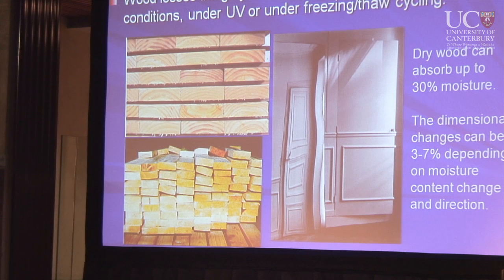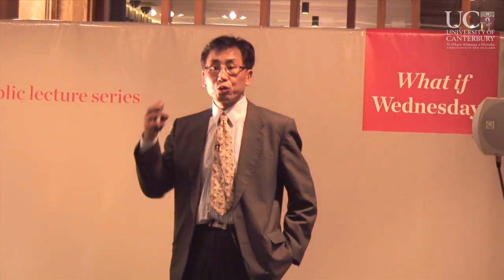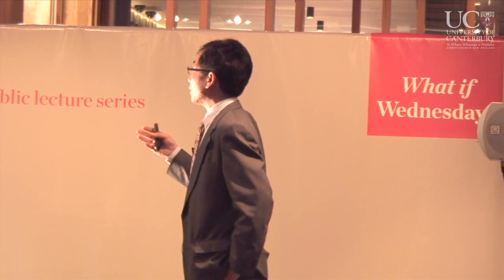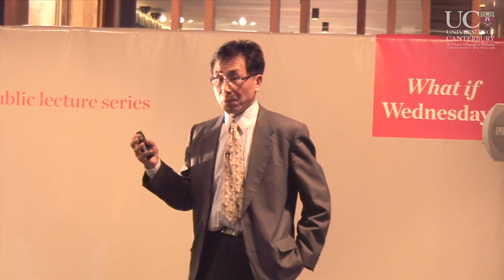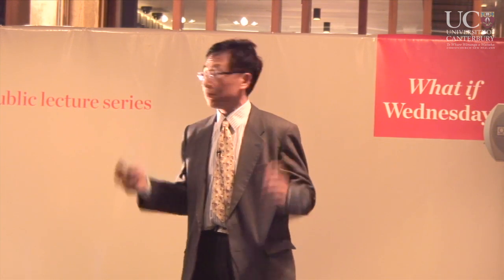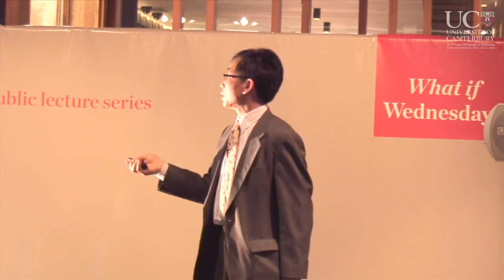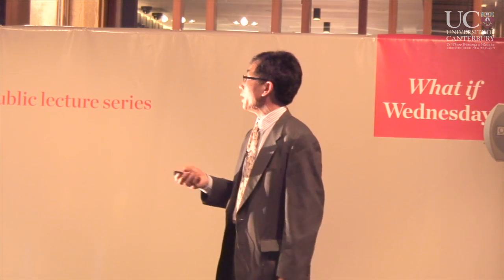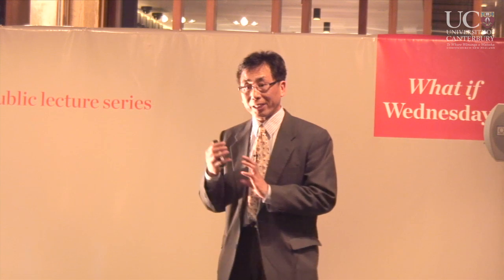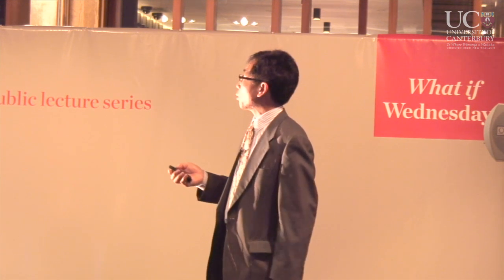Are you surprised? If you put the wood in a very humid environment, every kilogram of dry wood can absorb up to 300 grams of water. And at the same time, it swells, by 3 to 7% depending on the moisture content change and direction. So that causes a lot of problems.